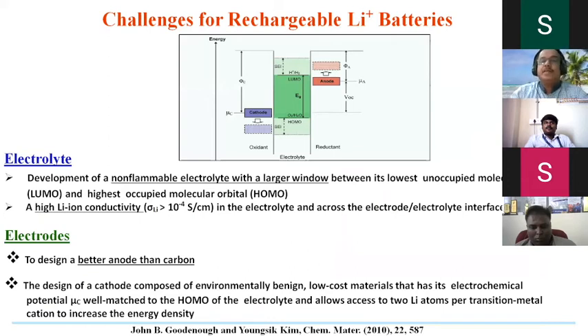That's the reason why people struggle hard to improve it. I think credit should go to Goodenough, because we are surviving on this technology and chemistry just because he proposed this technology. The challenges, if you ask me, are in electrolytes: development of a non-flammable electrolyte with a large window between its lowest unoccupied molecular orbital, what we call LUMO, and highest occupied molecular orbital, HOMO. So we have to think about developing non-flammable electrolytes with a large potential window. When developing these, you have to think about conductivity also. Lithium-ion conductivity should be greater than 10 to the power minus 4 Siemens per centimeter. And conductivity across the electrode-electrolyte interface is also needed. That's a very difficult task.